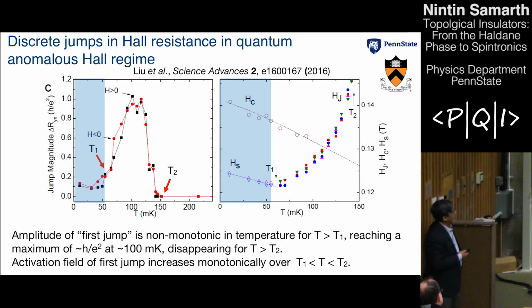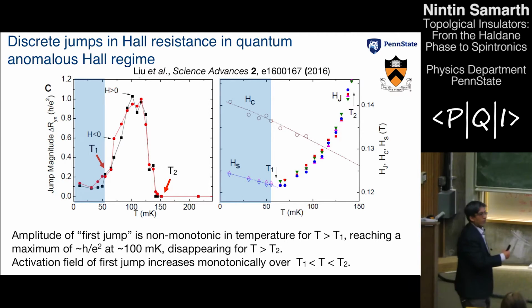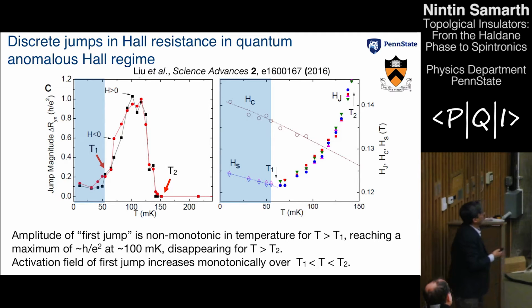Now, if you plot these two parameters as a function of temperature, you find that the jump magnitude of that first step increases to h over e squared. So essentially at 100 millikelvin, there's just one jump where you go from minus h over e squared to plus h over e squared, right? It's a dramatic jump like that. And then after that, that jump magnitude decreases, and it vanishes roughly where that energy gap is, so around 150 millikelvin. If you now measure the field at which the first jump occurs, then that field turns out to increase monotonically with increasing temperature, with no particular non-monotonicity, just a steady increase in temperature.